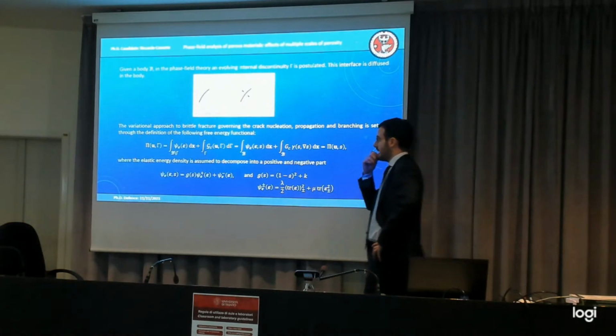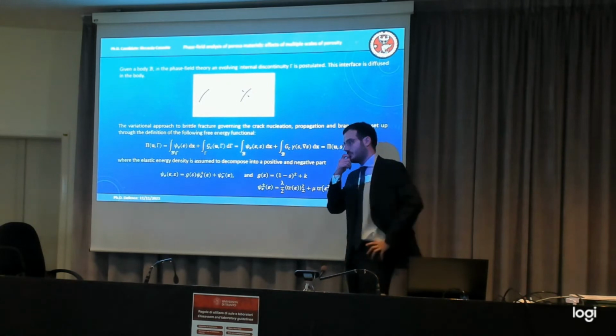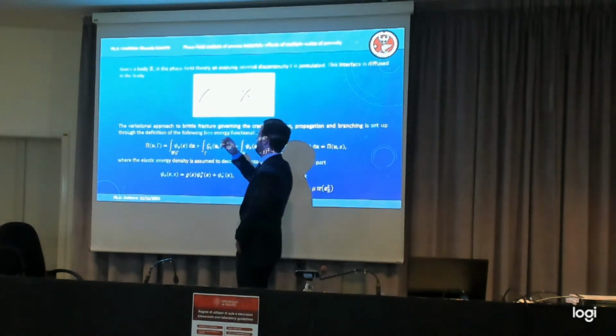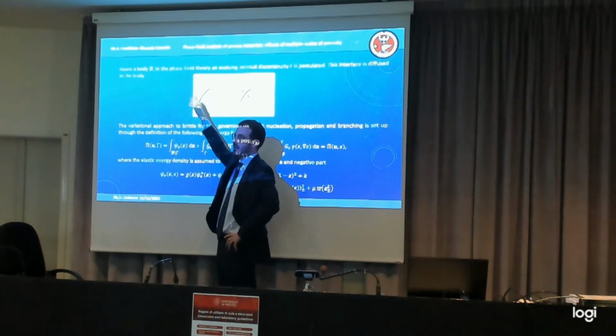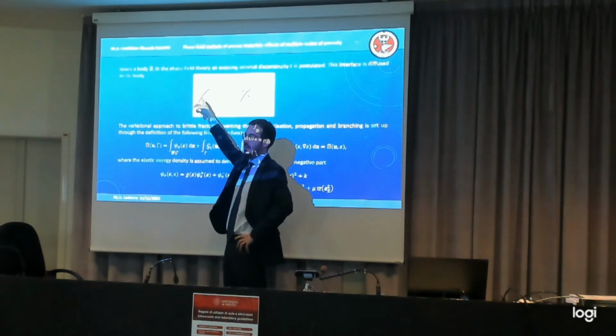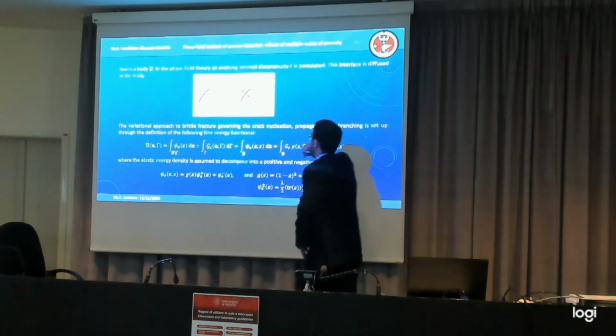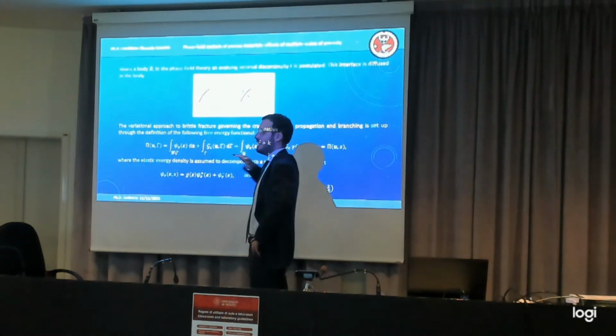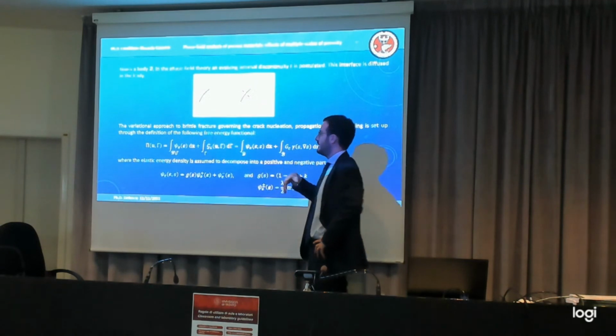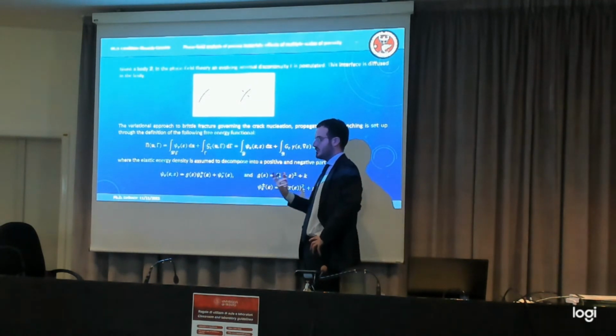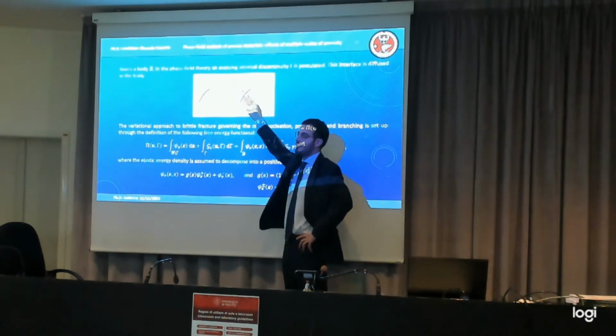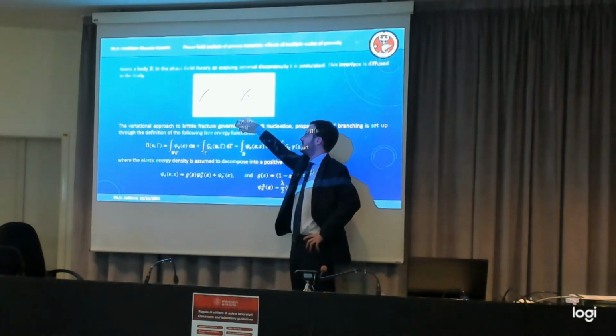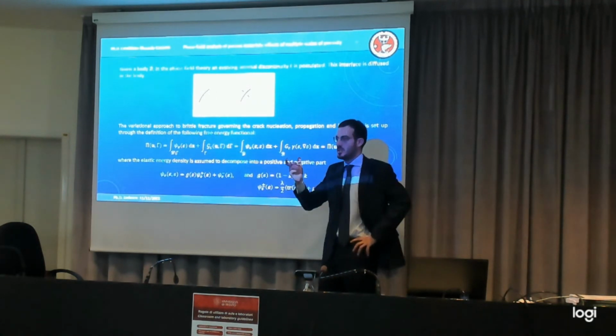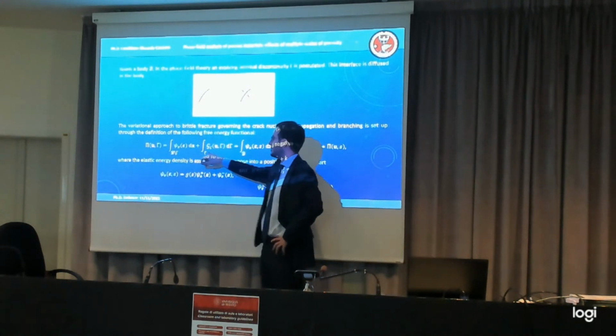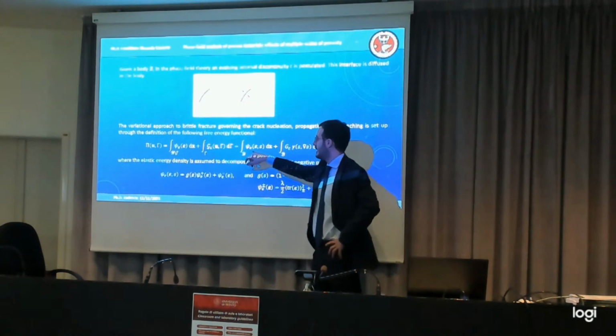The theory is based on an approximation, which is a topological approximation of the crack shape. So instead of imagining the body as a 3D element and the surface as developing inside, being itself an unknown of the problem, you imagine the damage to be diffused along the body, and you build up a scalar. You imagine there is a scalar function representing damage defined all over the volume. So cracks now are more diffused rather than sharp. This approximation is useful because it allows the total potential energy to be written in terms of only volume integrals.